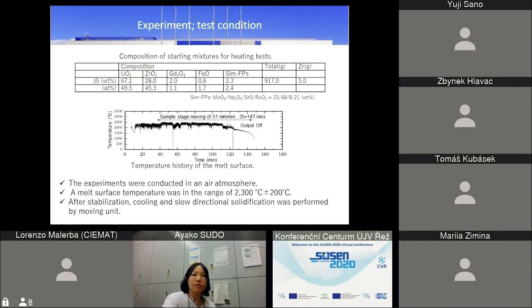And the next is the test condition. This is the composition of starting mixtures of heating test, J5 heating test. As the starting materials, uranium oxide, zirconium oxide, gadolinium oxide, FeO, and simulated FP was prepared in powder form, and the total mass of powder was approximately 900 grams.